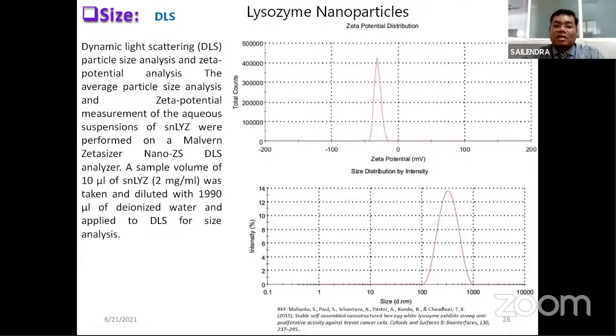So always try to achieve the maximum zeta potential that can be obtained from your nanoparticle. The more it is, the better it is. So the chances of aggregation of your nanoparticles will be less. If the peak is close to zero, you will have more aggregation in such kinds of nanoparticles. Moreover, whenever you are doing this nanoparticle analysis, particularly with respect to DLS or dynamic light scattering analysis,